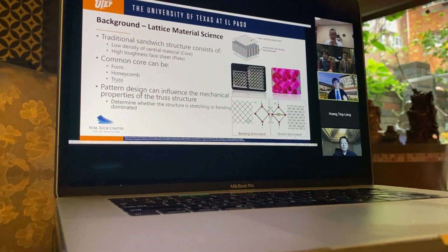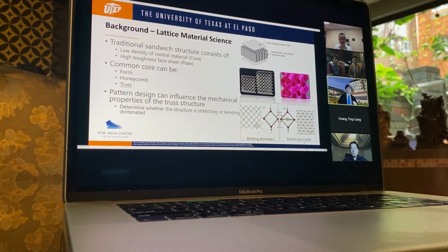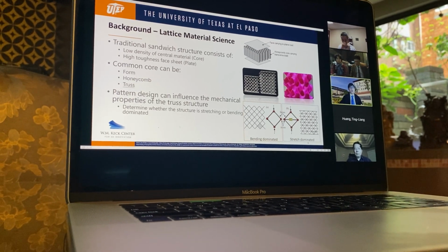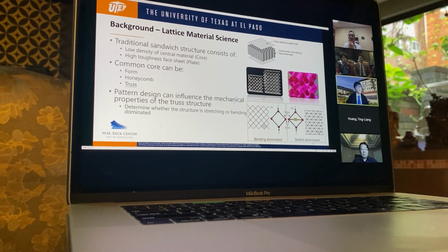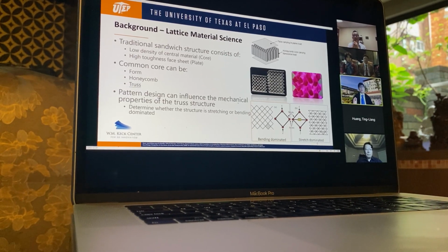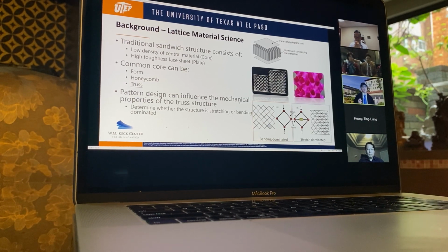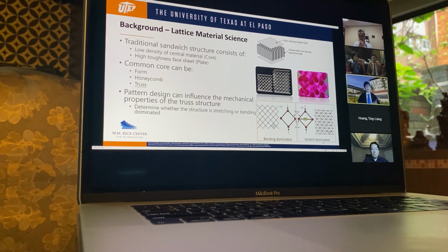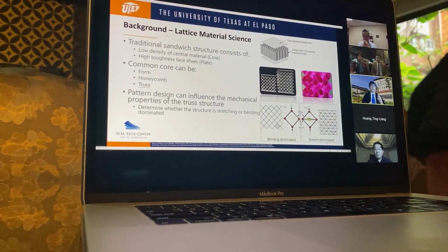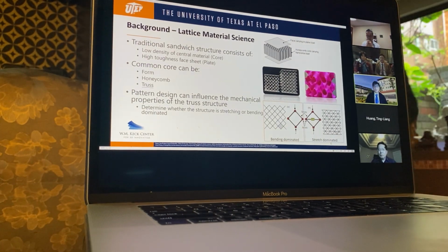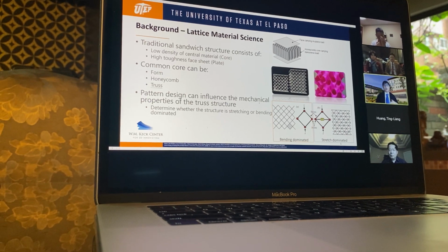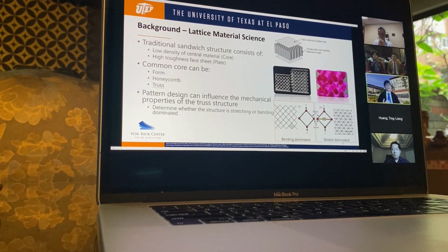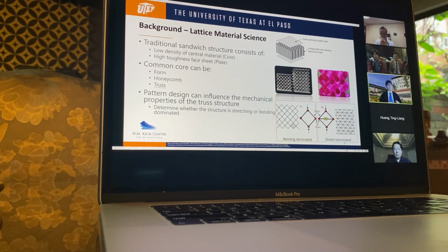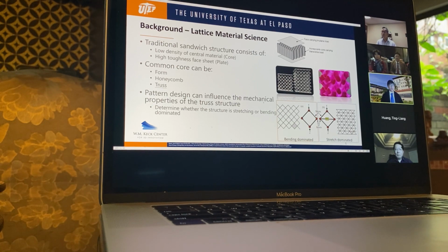We chose the truss structure because of its two components, the joint and the strut. So it's more intuitive for us to design within a pattern. We can manipulate a design aspect to control the mechanical properties of the structure by designing a different pattern, like a stretch dominating or bending dominating pattern. The criterion to distinguish whether a pattern is stretch dominating or bending dominating is the connectivity. If the joints connect with few struts, the pattern belongs to bending dominating, and the stress will focus on the joint when the structure is under loading, which produces a rotating behavior in this part. This mechanism gives the structure higher energy absorption.